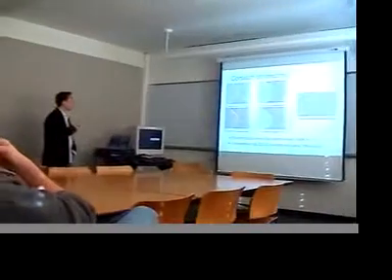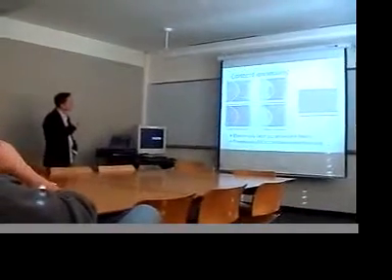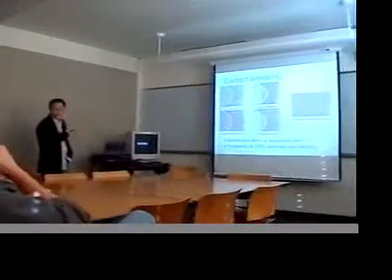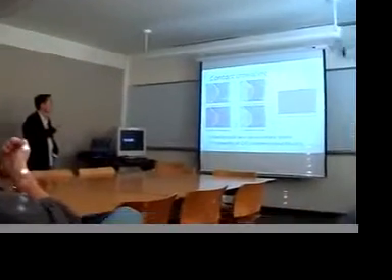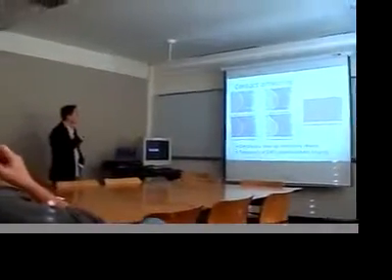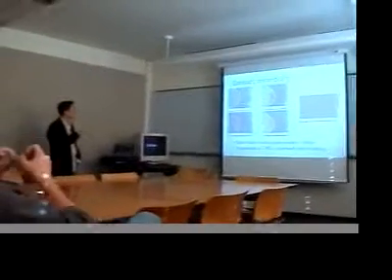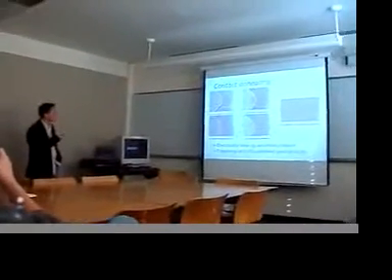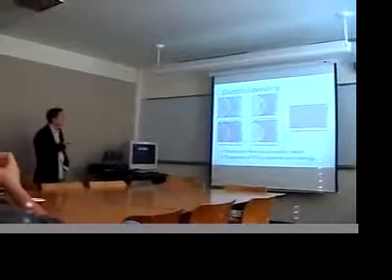We've also tried, going back to the contact issue, some kind of contact annealing to really find out whether our contact actually contributes a lot. As you can see here, we thought that since we already have an on-chip heater, we would just use it and heat at one side. You can see that the catalyst all diffuses into the silicon. Unfortunately, everything breaks, and they break in a very interesting manner.